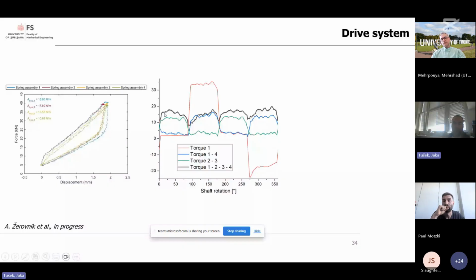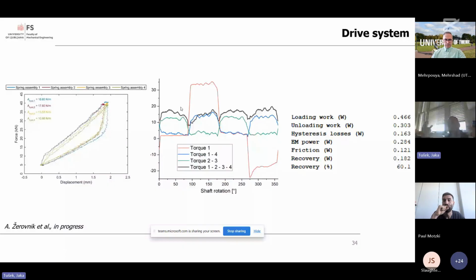We also evaluated the work recovery efficiency. Of course, if there were no friction, the entire energy that's released would be used by another regenerator. But we have two bearings in the system and very high forces, and this results in only 60% of the released energy actually being used efficiently, which is not yet the goal, but it is a decent value. We would like to be at 80 or 90%, and we have some ideas how to further improve that in the future.